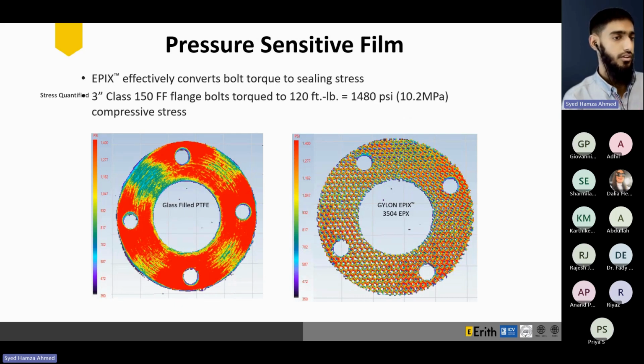This is a stress quantified diagram where you can see a glass filled PTFE Gylon as compared to a Gylon EPIX model. This is a 3504 Gylon EPIX model that we were talking about. Here, as you can see on the left, there are stress concentrations, whereas there are regions where the stress is not uniformly transferred, the bolt stress is not uniformly transferred all throughout the gasket, and we see areas of higher stress concentration and areas of lower stress concentration. This example is from a 3-inch nominal pipe size and a pressure class of 150 full face flange, which was torqued up to 120 foot-pounds.